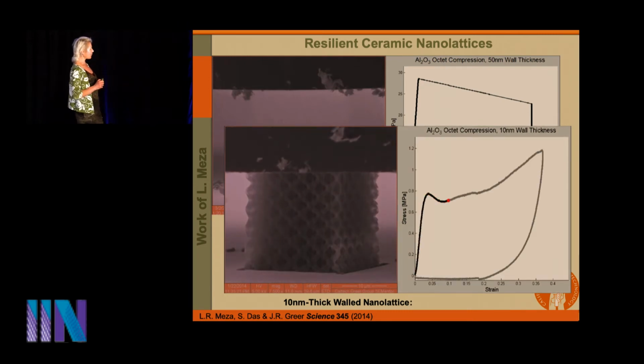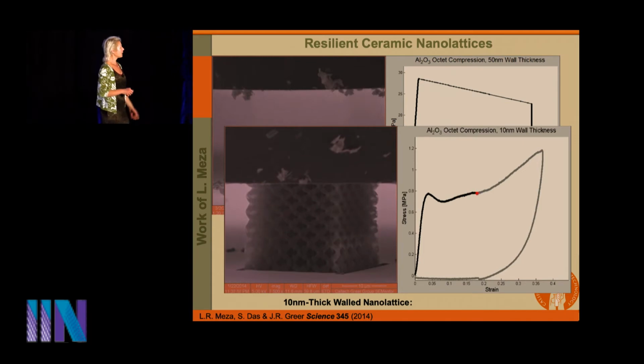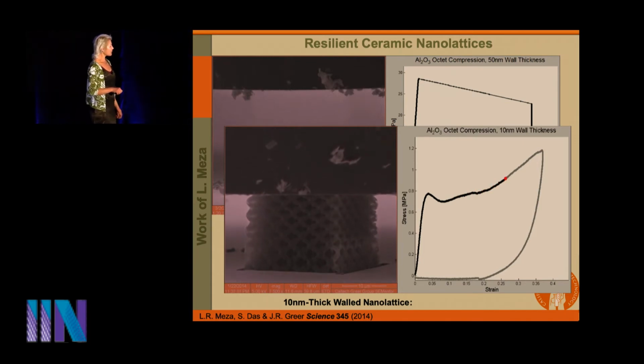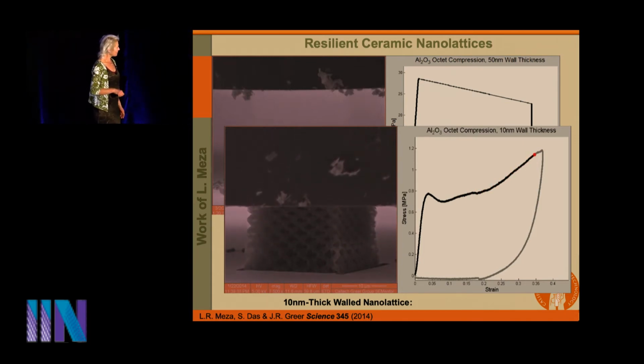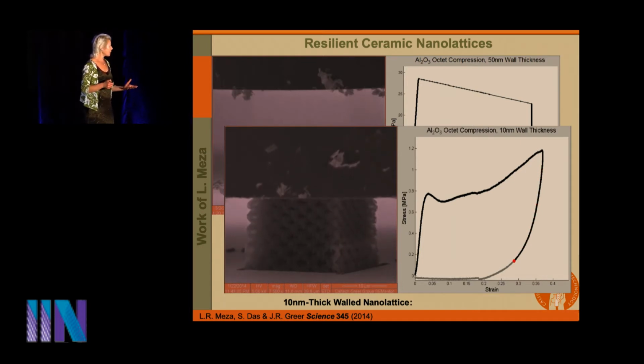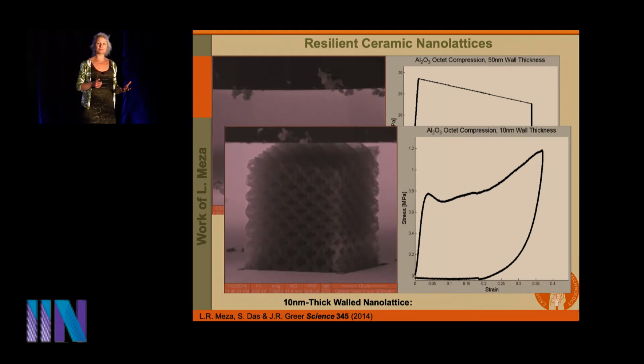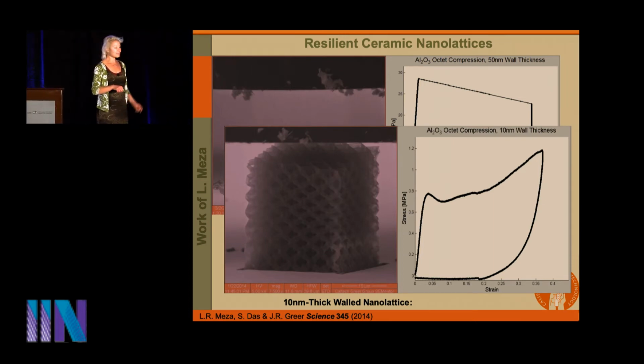And so here we are. This is my former student, Lucas Meza, compressing this, and he's compressing it almost to 50%, and we're waiting for it to crush and to die and to fracture in every way. And this particular ceramic thinks it's a sponge. So if that doesn't convince you that there is in fact a size effect, I should just turn around and fly back to California right now. The only difference is the wall thickness, but the deformation behavior is drastically different.